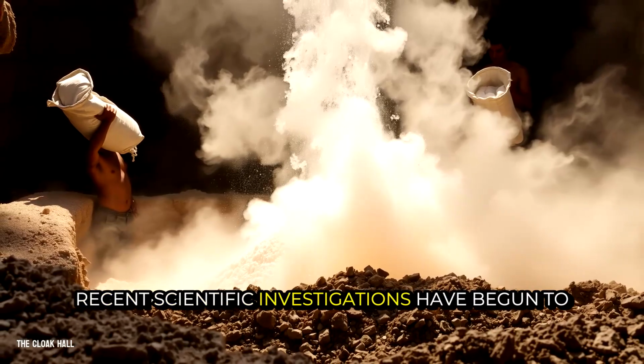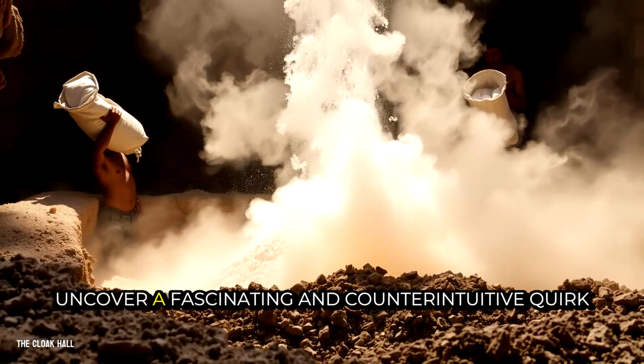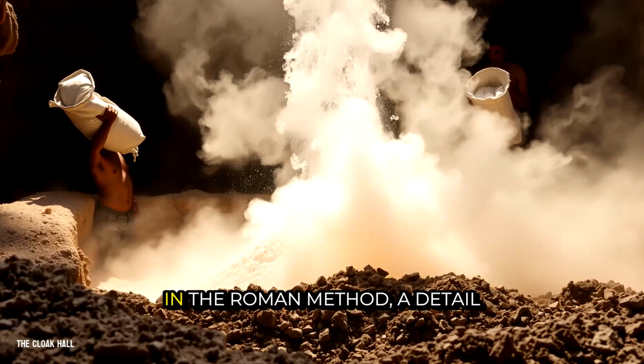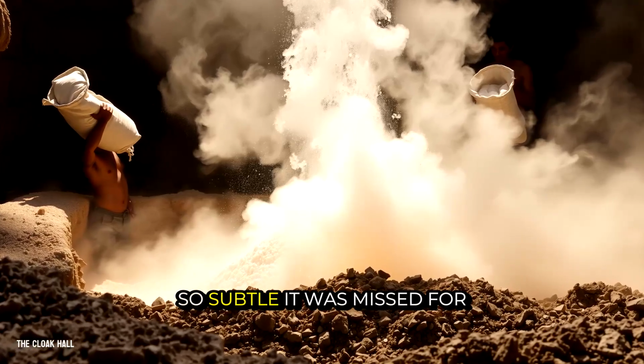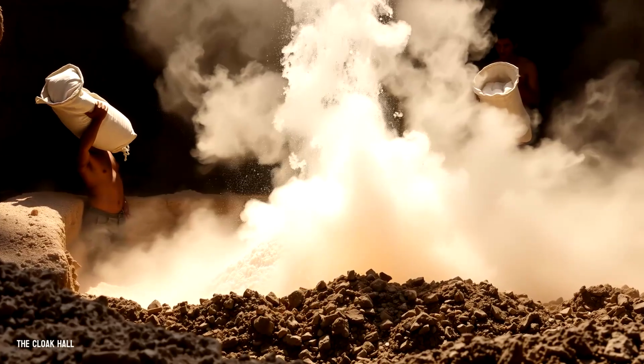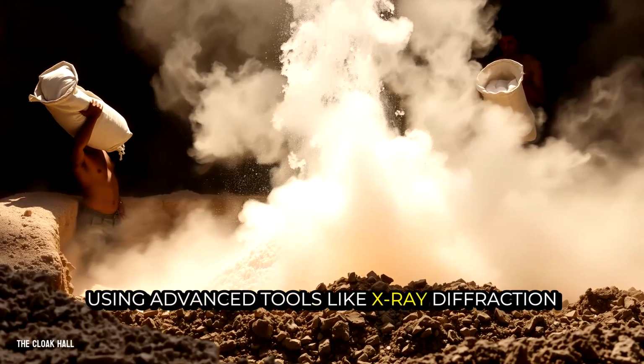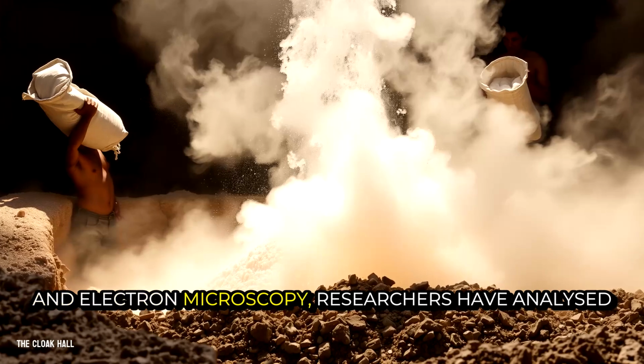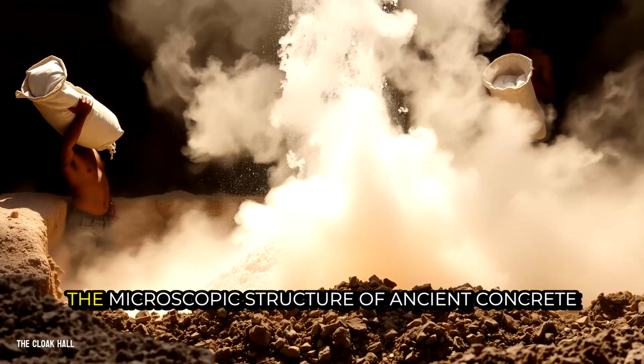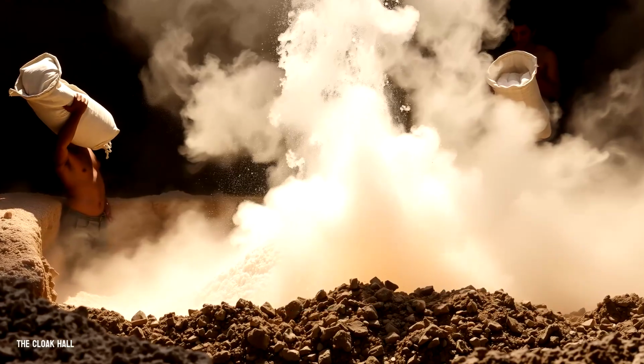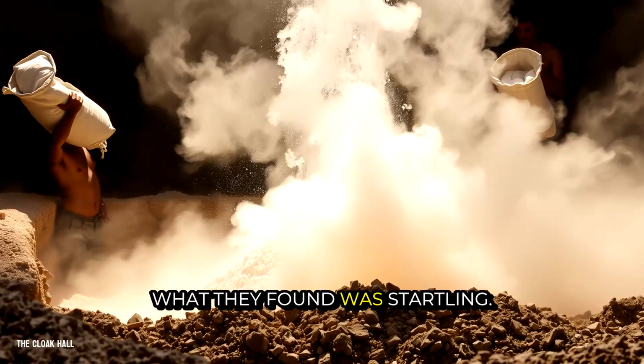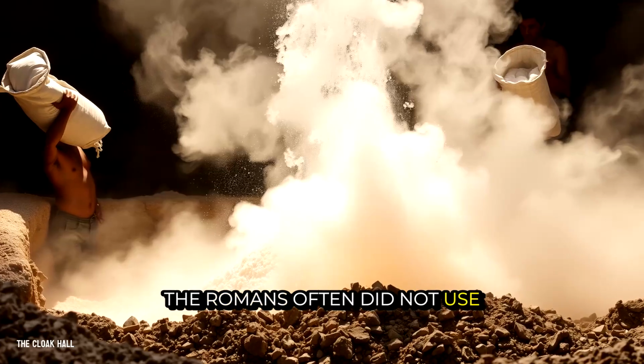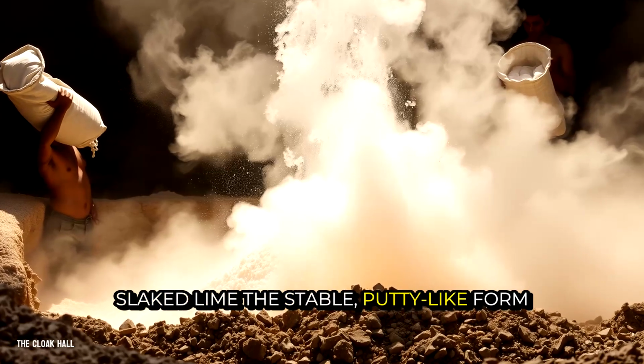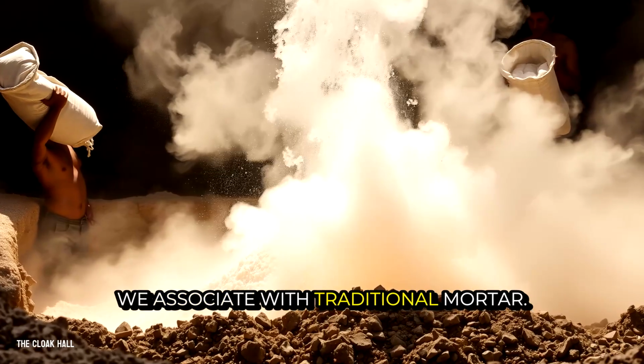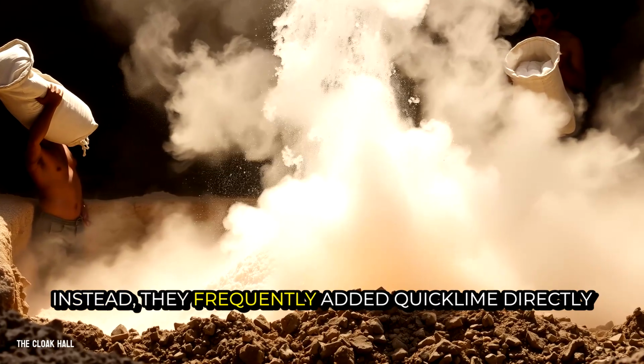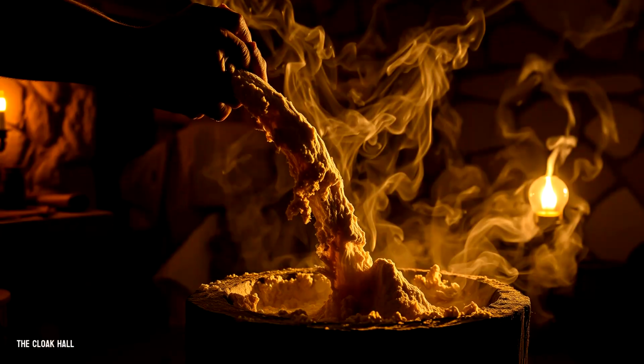Recent scientific investigations have begun to uncover a fascinating and counterintuitive quirk in the Roman method, a detail so subtle it was missed for centuries. Using advanced tools like X-ray diffraction and electron microscopy, researchers have analyzed the microscopic structure of ancient concrete samples. What they found was startling. The Romans often did not use slaked lime, the stable, putty-like form we associate with traditional mortar. Instead, they frequently added quicklime directly into their mix.